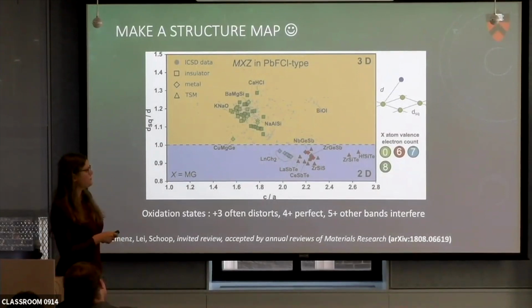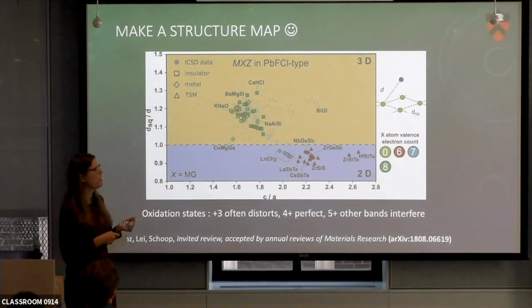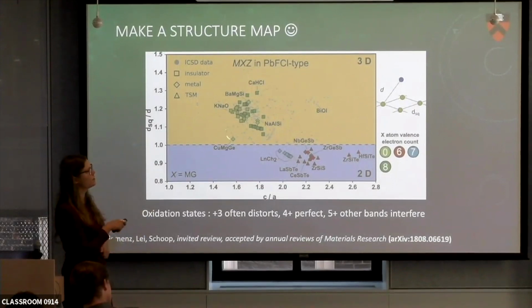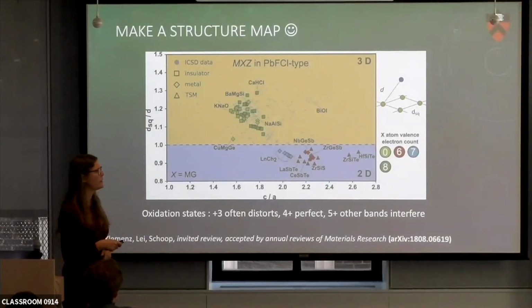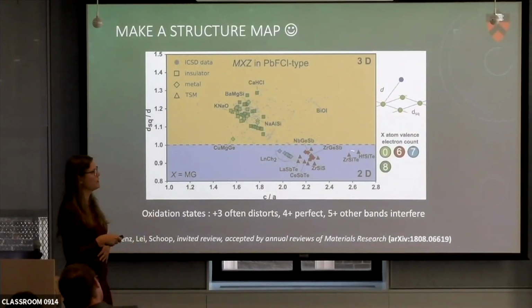And then we gave the points colors based on the electron counts, which should also tell us if hypervalent bonds are possible or not. And the first thing that we realized is, okay, 0 and 8 electrons, there shouldn't be any chemical bonds because everyone should be happy, right? Counting to 8 was the rule. And all these green spots are up here, where the distance factor fails us. And for 6 or 7 electrons, where some chemical bonding needs to be there, the points are down here.